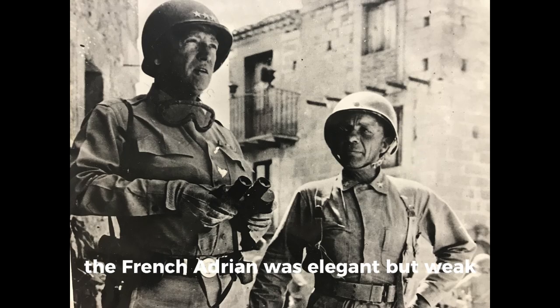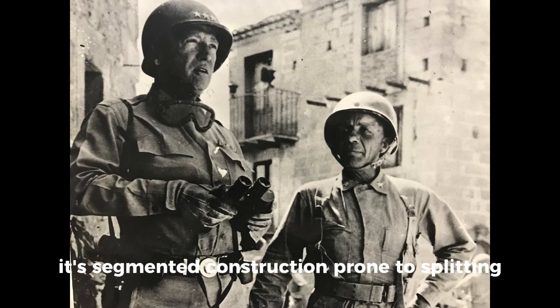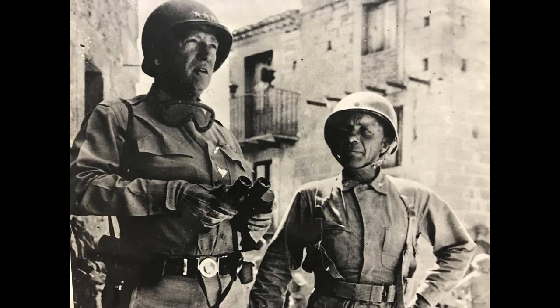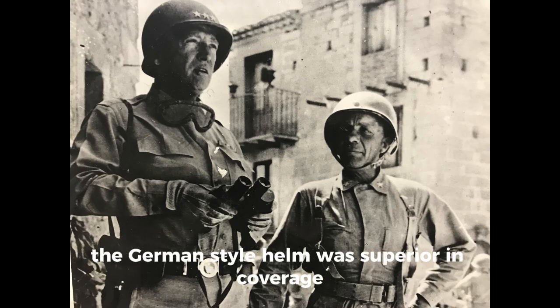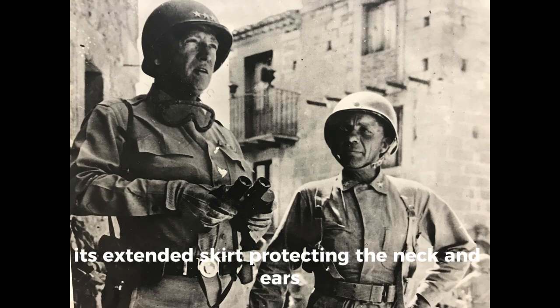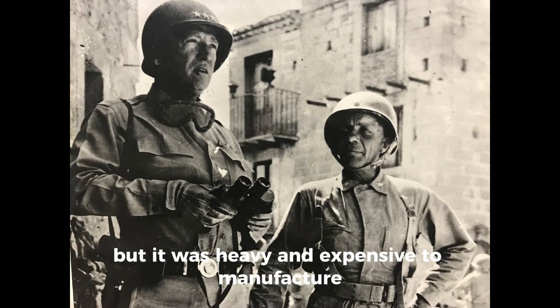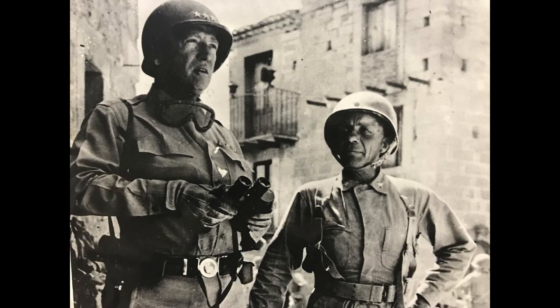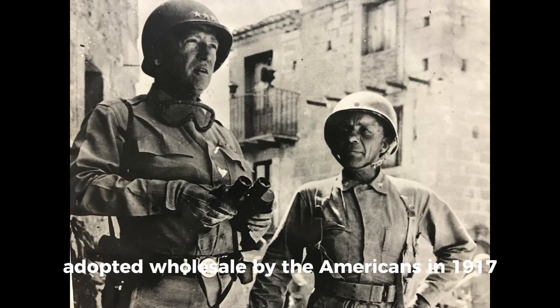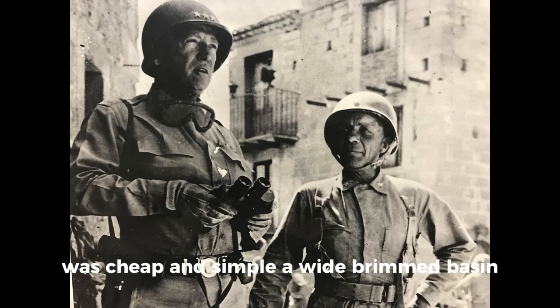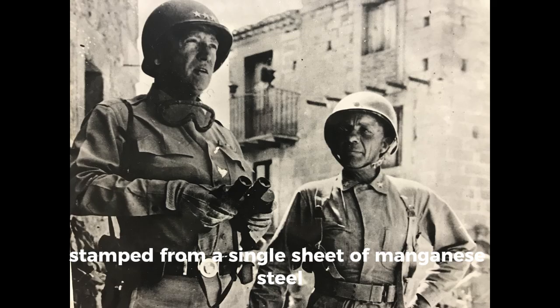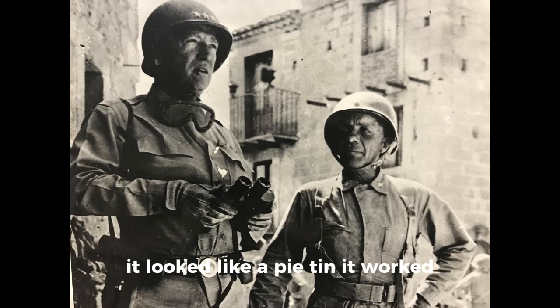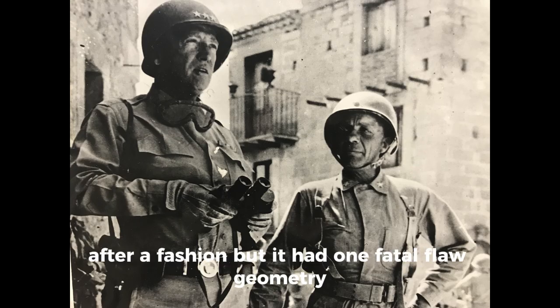The French Adrian was elegant but weak, its segmented construction prone to splitting. The German Stahlhelm was superior in coverage, its extended skirt protecting the neck and ears, but it was heavy and expensive to manufacture. The British Brodie, adopted wholesale by the Americans in 1917, was cheap and simple. A wide-brimmed basin stamped from a single sheet of manganese steel. It looked like a pie tin. It worked, after a fashion. But it had one fatal flaw.